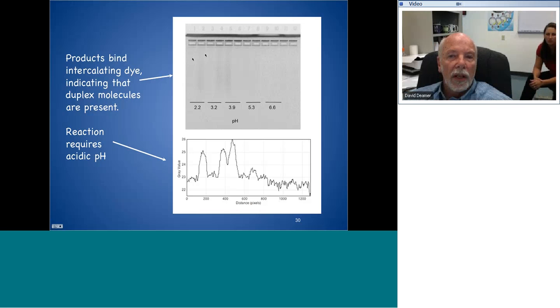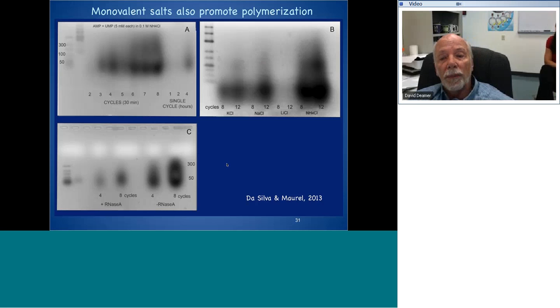There you can see it. These are the long, many strand lengths all the way from probably 30 mers down to here, up into the 200 mer range up here. Notice also that this occurs at low pH ranges, but not at high pH ranges, as predicted from that mechanism. And here's a scan showing how this works. So what I got from this, when we first began to see this, is that maybe we were having double-stranded species being produced when both AMP and UMP were present.